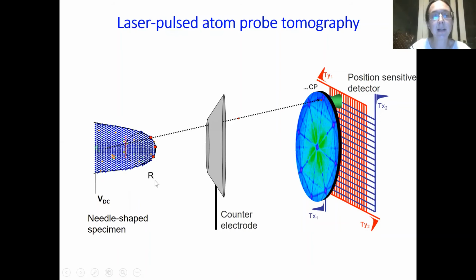And if you apply a high enough electric field, it tends to force atoms to evaporate, ions in fact, to evaporate from the end of the tip. What we're going to do in this case is hold it just below the threshold that would be needed for that field evaporation. Then we're going to hold it at quite a low temperature and just warm it up a tiny bit with a laser pulse.